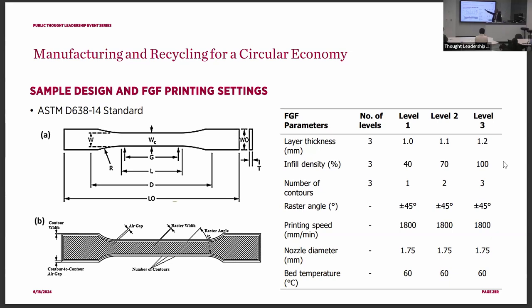So for the printing parameters, we look into the layer thickness, the infill density, number of contours, raster angles, printing speed, nozzle diameter, and even bed temperature. The bed temperature is just the build plate temperature. We also look at different levels of layer thickness. So three levels: 1.0, 1.1, 1.2. And for the infill density, we look at 40, 70, 100%. And the number of contours, so that's the layers, that's 1, 2, 3.